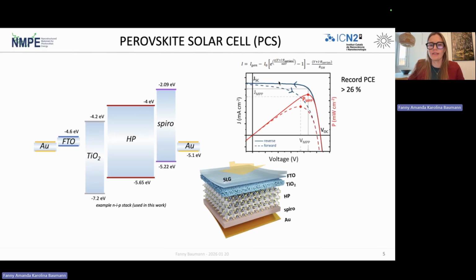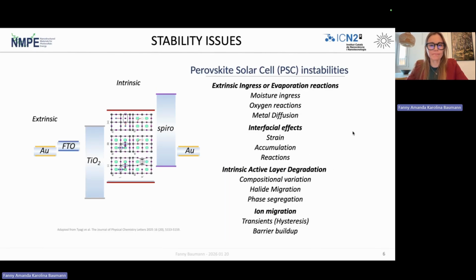We see that it's important to generate sufficient electronic carriers inside the device and also have a large internal electric field and also extract device charges efficiently so that we can get the highest possible power output. So record devices are reaching power conversion efficiencies above 26%. Here we are optimizing very much for stability, so we are more focused on the longevity of the solar cell than on reaching record efficiencies.